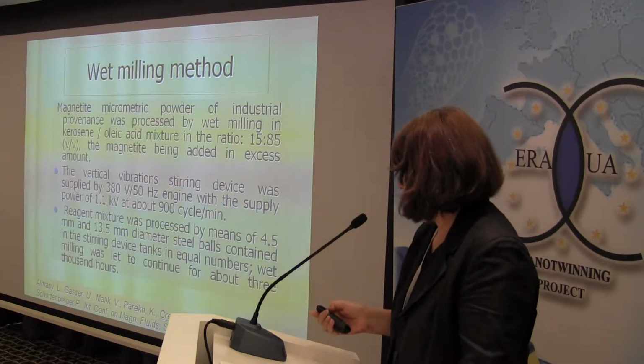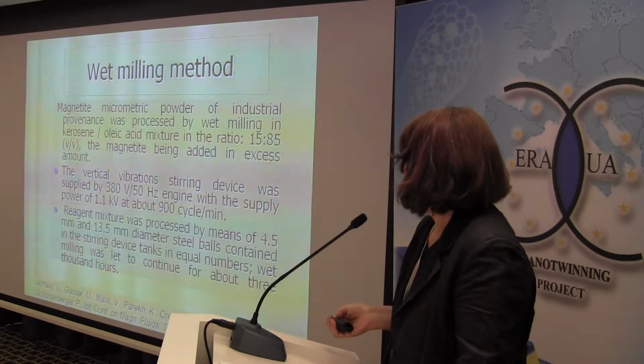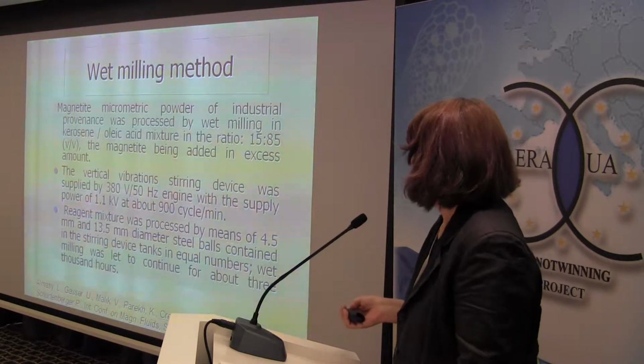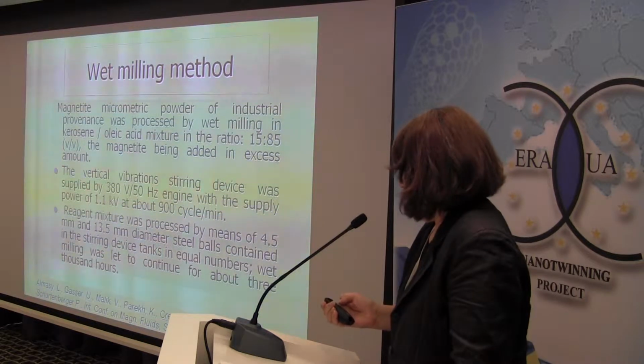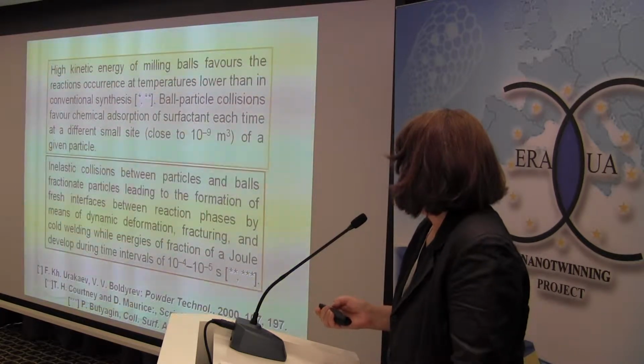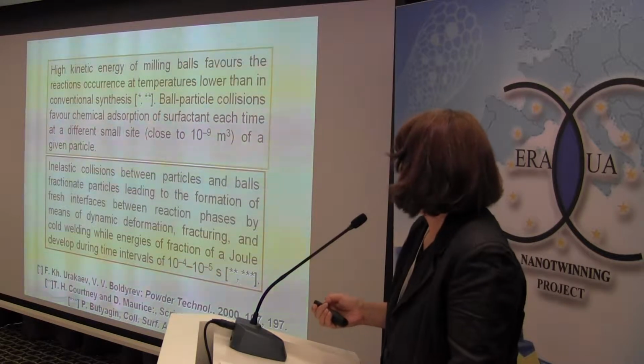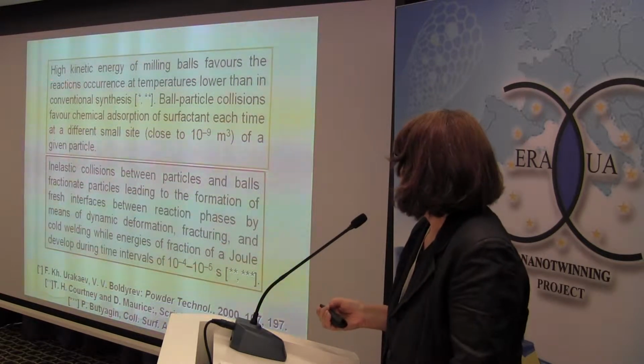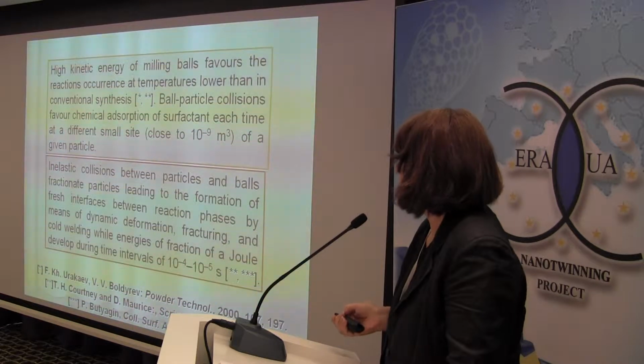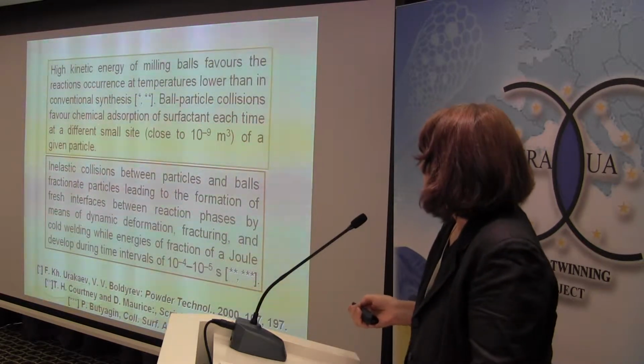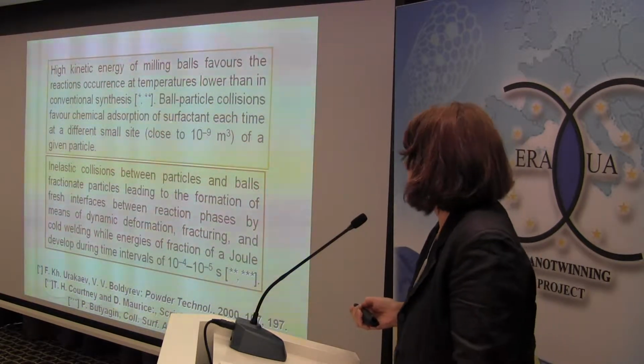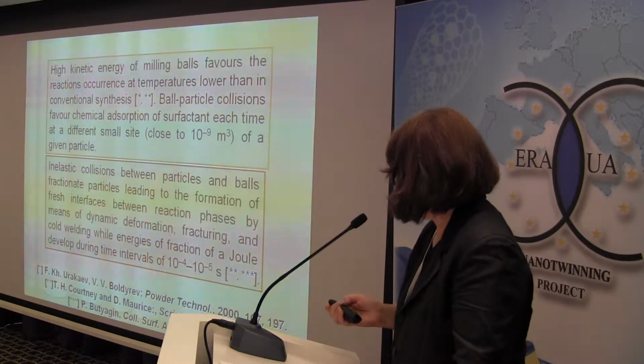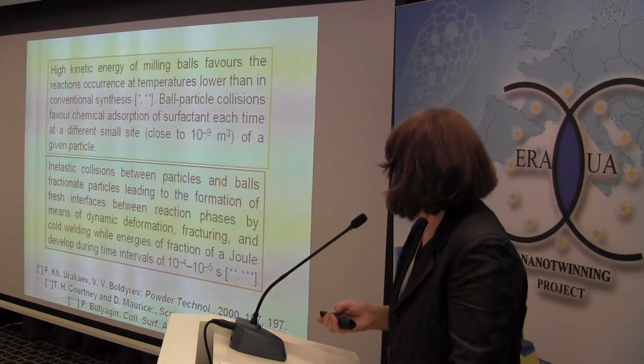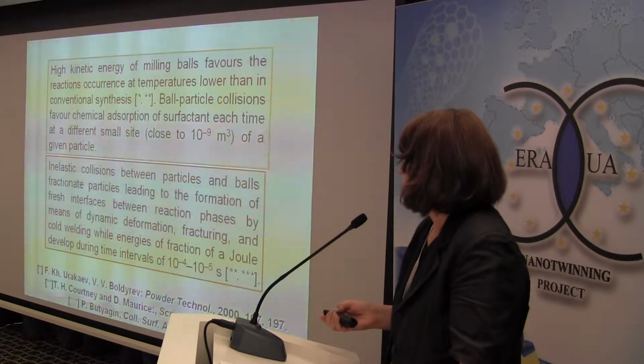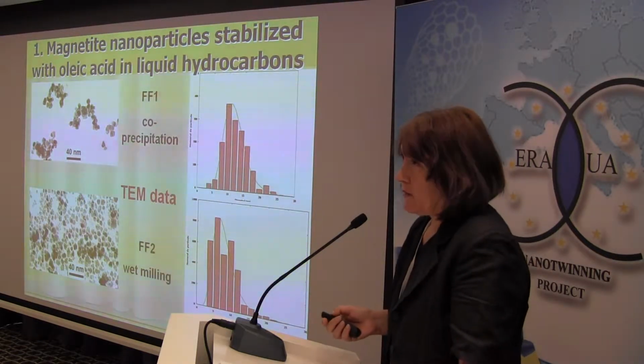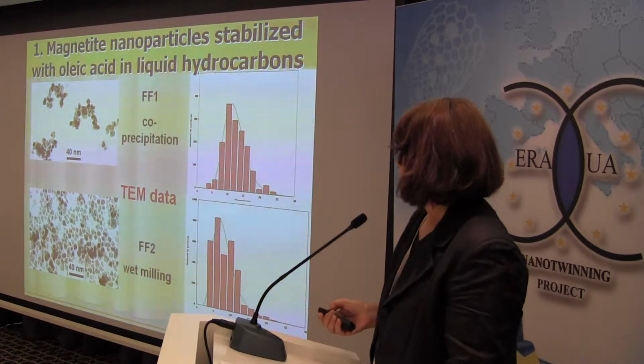Because the wet milling involves the strong collisions between the steel balls with the magnetite microparticles, a process during which high kinetic energy is released, and it is able to favor chemical adsorption of surfactant, the oleic acid in this case, to the nanoparticles, and to provide a good stable ferrophase suspended in hydrocarbons.